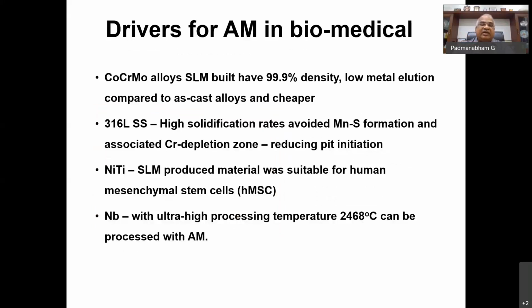Why is it attractive in the biomedical industry? I mentioned a couple of advantages from the geometry point of view, the osseointegration point of view, and the customization point of view. From the material point of view, some of the popular materials used in the biomedical industry are cobalt-chrome-moly alloys. With additive manufacturing, it was found that you can achieve 99.9% density and low metal elution compared to the as-cast alloys, and cheaper also. Low metal elution means less toxicity in the body also. Similarly, stainless steel 316L is a very popular material. High solidification rates avoid the manganese sulfide formation, which results in chromium depletion and pitting corrosion in these parts, when you do additive manufacturing using the laser-based powder bed technique.